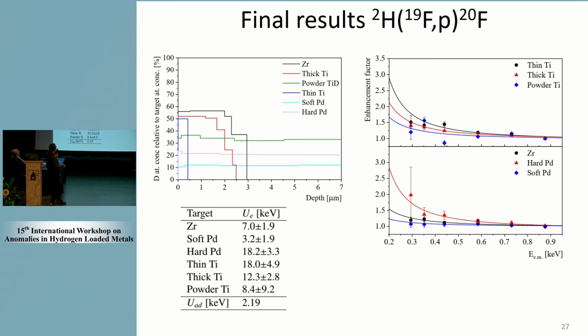This was the case of zirconium and thick titanium. And this thin titanium was made such that we evaporated titanium onto a tantalum backing and then implanted it, and you can see that deuterium is only in the titanium layer, not in the tantalum layer. So we got different results for electron screening. Except for this soft palladium, they are all above electron screening.